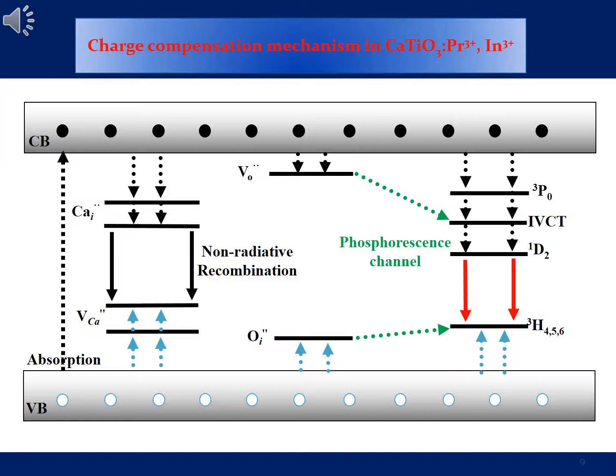Now, our materials often, which we dope with praseodymium ions, which is now a luminescent center, upon exciting, some of the electrons will directly de-excite to the luminescent center and give us spontaneous luminescence. Now, in the case where we have shallower oxygen vacancies, electrons will take place in a process of electrons being stimulated by thermal energy of the ambient temperature to the conduction band all the way to the luminescent center, and now this opens up a channel which we call persistent luminescence. And in order for us to enhance this persistent luminescence, we need to go back to the structure of our